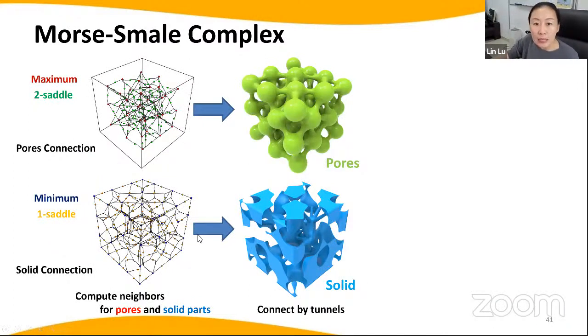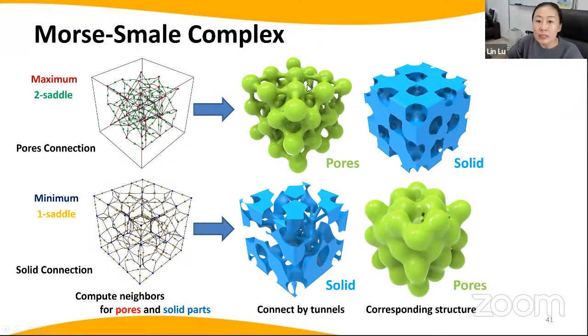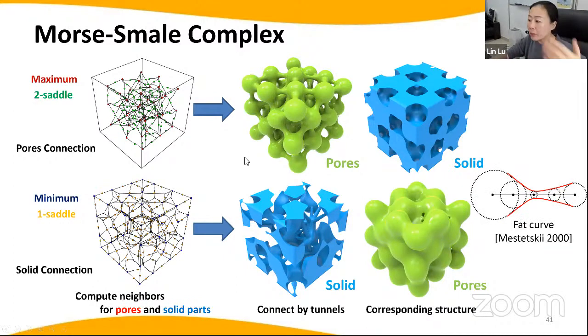So let's see a specific example. Here we want to connect the pores, and then we need to consider which are the best connection options for the pores, and we follow the MSC cells consisting of the maximum and 2-saddle points. So we get these connected pores, and we also have the solid one. If we consider connecting the solid part, which is not often used, we can still guarantee the solid part to be connected using the minimal and 1-saddle points as the complex element. For the connection, we employ the fat curve, which is a trace by a moving sphere of changing radius like this one. Okay, so that's the basic technique.